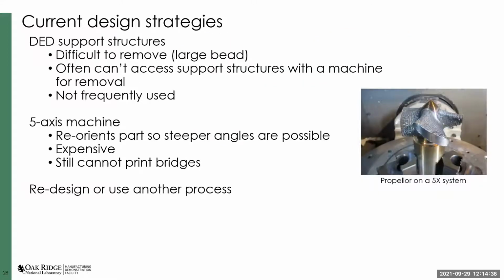There have been some strategies to try and mitigate this and to problem solve this. There has been some minimal work in support structures in DED, similar to support structures that you might see in plastic 3D printing, desktop 3D printing, but they're much more difficult to remove and much more difficult to design in the first place. Again, because your bead is so large, it's much trickier to machine it off at the end. It's much trickier to get the lattice type support structure to support the weight of your bead. So they're really not frequently used. I've been at Oak Ridge over a year now, and we have, say, 3 DED systems, and I've never seen a part printed with a support structure.